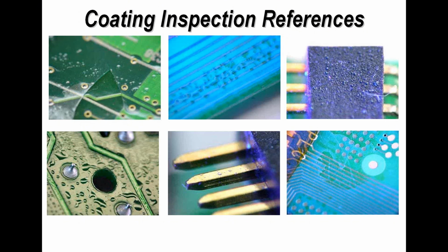On the center area we're seeing measling, where the coating is slightly lifting on the edges. Top right hand view is contamination on a component, on a connector, and this is easily seen with UV light. Bottom left hand view, I show de-wetting of the surface, and literally this is where the coating is wetting small areas. It's been coated, but then it's pulled back. It's just like solder de-wetting on a printed circuit board pad or component termination. And then contamination on connector pins in the second image on the bottom row.